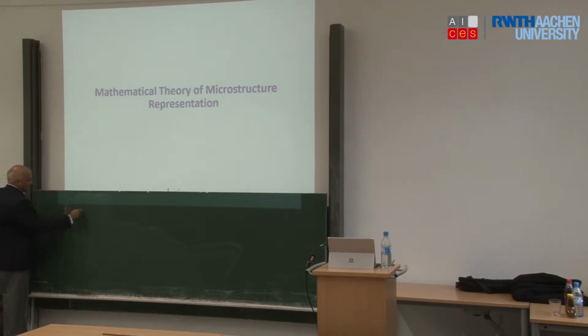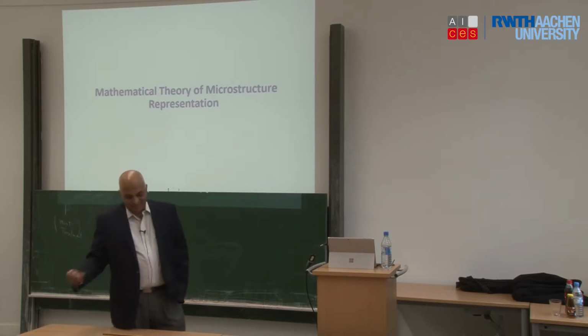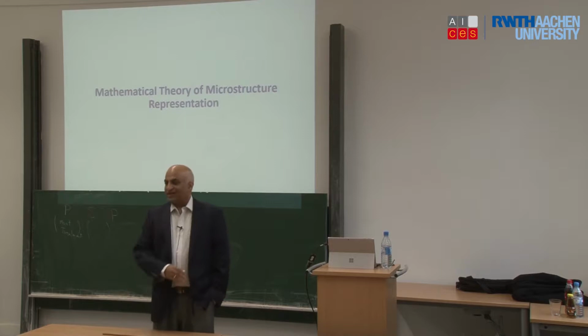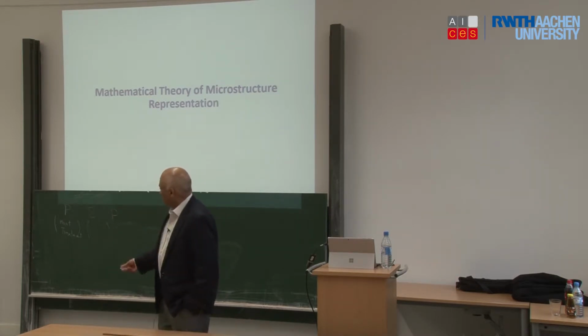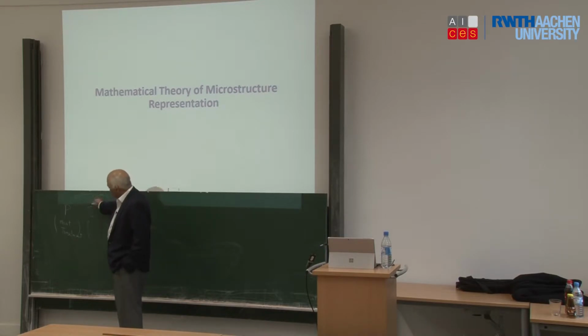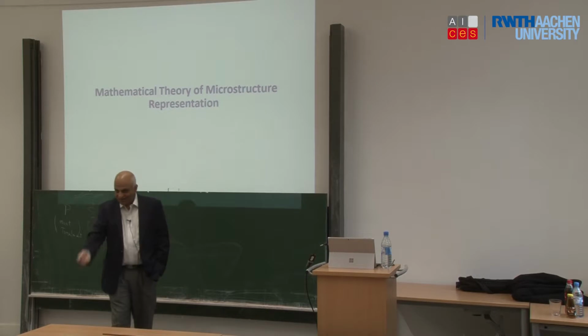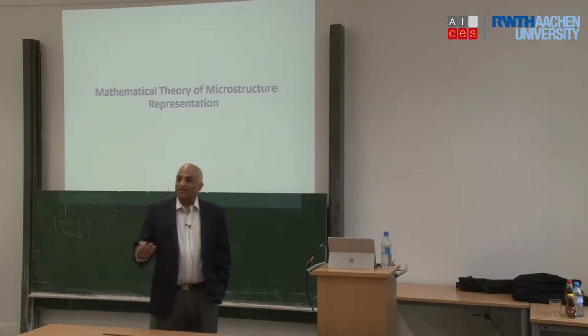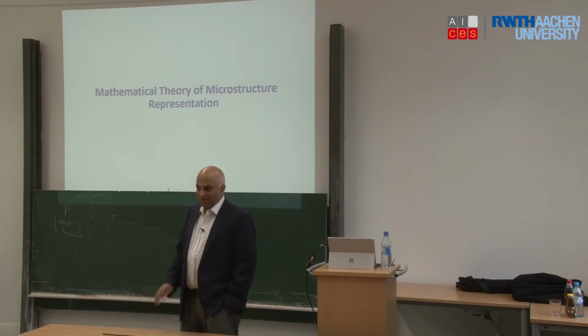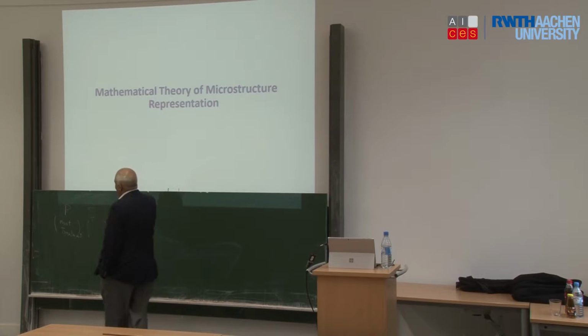So, process structure property, right? Based on what you said, Julian, all the heat treatment and all the stuff comes in here, right? And this is structure. So if you have aging, more solid solution, less solid solution, segregation to grain boundaries, porosity, vacancies. In fact, in mechanical properties, when we talk about structure, we are simply talking mostly about defect distributions. We're really not even talking about the atomic structure itself, because mechanical properties are a lot more sensitive to defects and grain boundaries. Everything is included in there. So in our definition, all of that goes into here.